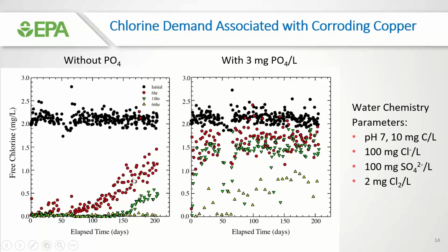in these recirculating loops. We always started out with about 2 milligrams per liter, and at the end of various recirculating times, you can see how much chlorine is left. The point being is that without phosphate, we often don't have a chlorine residual. But when we add phosphate, even from the beginning of these experiments, there's always a chlorine residual. And this is really, really important.